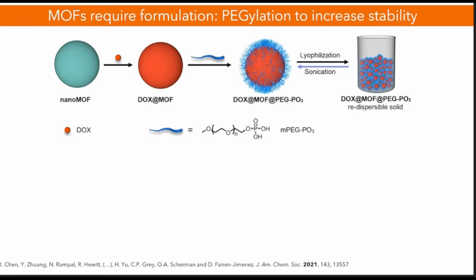And once we have been able to synthesize these materials, we found that that's not the only limitation. We also need to reformulate these metal organic frameworks, and this goes beyond the predictions that we can have with Monte Carlo simulations, because we want a material that is highly not only biocompatible but also has very good hydrochemical stability. If you remember, these materials were not amazing in terms of stability, and something very interesting is that it doesn't matter how robust the material looks in the lab. As soon as we have some phosphate salts, which is something we typically have in buffers in biological applications, these materials will get degraded very, very quickly. So we need to protect them.